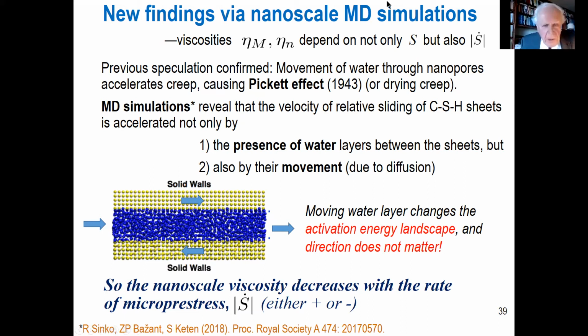So one phenomenon like this is the Pickett effect that I mentioned. This effect was explained, but only partly and insufficiently, by microcracking. It was clarified finally by MD simulations done by Sinko and Keten at Northwestern with me a few years ago. You have two solid walls modeled molecularly. Then you fill the gap with water molecules shown here, and if water molecules are present, because it's hydrophilic, creep is on a microscopic scale. We believe it's always shear creep. Creep is always sliding of these sheets, not widening or something.